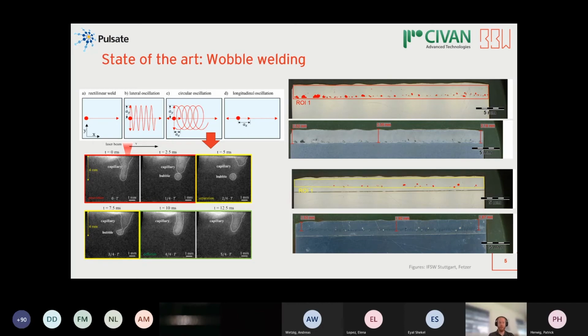It is a great technology, but the acceleration and the speed is limited by the mirror masses. So state of the art is a maximum of 4 to 6 kilohertz of wobble frequency with this system. Therefore, wobble welding in combination with high-speed welding is until now hardly possible. Also mentioned today, investigations with pressure cast aluminum, which have a very high base porosity, suggest a much higher necessary frequency. So this is another interesting investigation topic, not only for us.